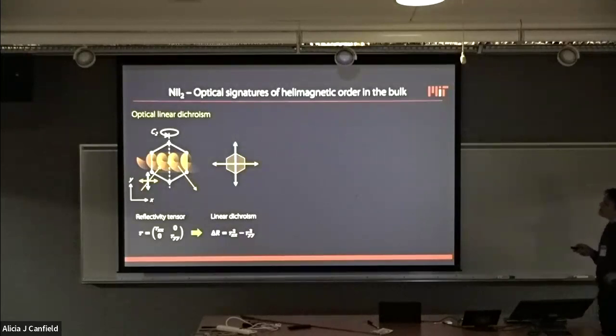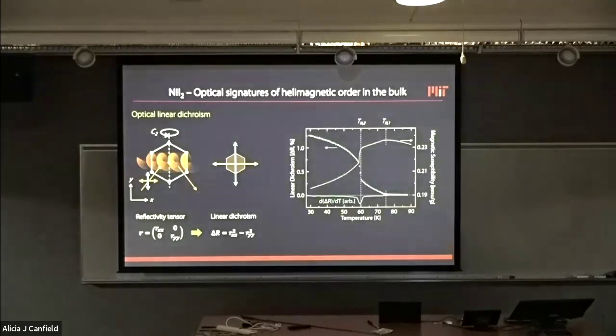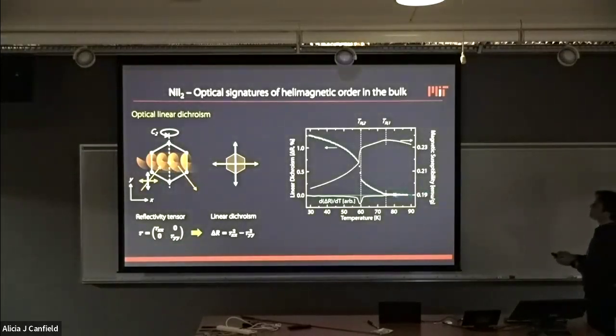So the most basic type of measurement you can do is optical linear dichroism. The moment you develop a single-Q spin helix, you break your rotational symmetry. So you expect that the optical response for light polarized perpendicular versus parallel to the helix will be different. This gives you a reflectivity tensor in this form, produces linear dichroism, and we can see the signature of linear dichroism very clearly correlating with the transitions as seen in the susceptibility. In the bulk, we see that the linear dichroism jumps at 59 Kelvin. This appears to be a first order phase transition, although that's not settled yet.